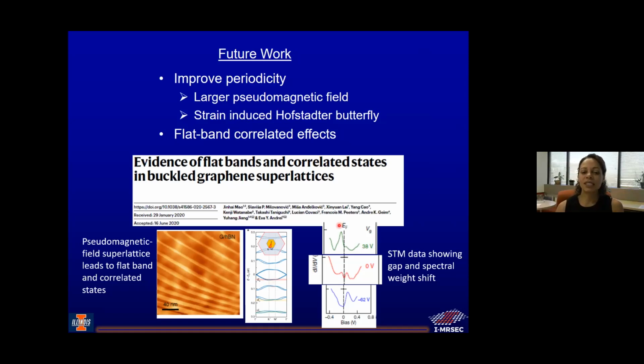And in fact, when they did scanning tunneling microscopy, what they saw was a gap appearing around zero energy and shifting of spectral weight to the left and the right of the Fermi energy at higher gate voltages, which is consistent with what they'd expect for some sort of correlated effect due to a flat band. So this was really exciting to us because, again, this is STM, but these sort of effects have not been seen very strongly in transport, and that's the next thing we want to look at in these nanopatterned graphene devices.